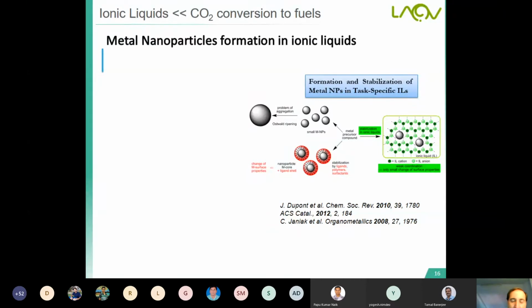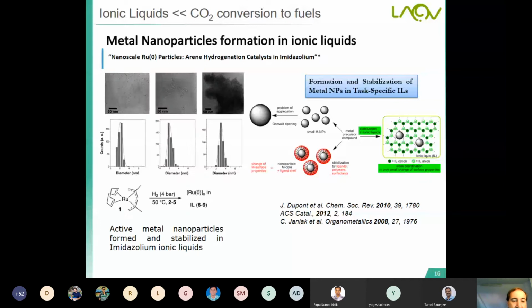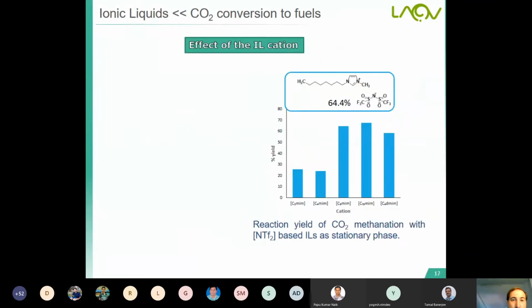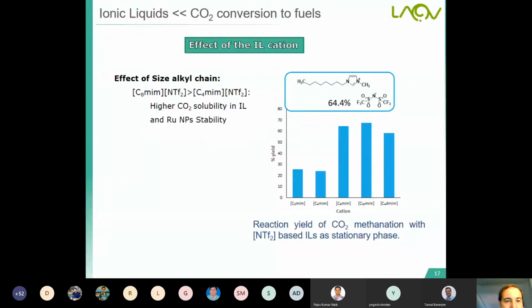This was proved by many groups, including Jairton Dupont and Janiak and other groups. And they proved that the active metal nanoparticles form and stabilize in imidazolium ionic liquids. And after that, we tried to check the effect of the ionic liquid in this reaction. The effect of the ionic liquid cation, the size of the alkyl chain, is crucial.